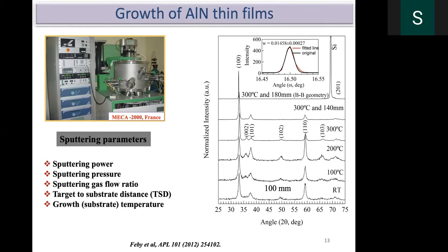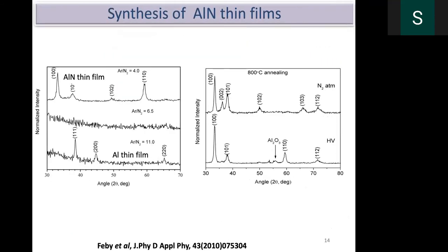crystalline films. Well, we started with aluminum nitride films, but initially we kept everything constant other than the argon to nitrogen ratio. See, argon to nitrogen ratio, if I have 11%, that means argon is higher and nitrogen is very small. In such a situation, the film is completely aluminum. Maybe a few nitrogen will be there that I did not show in the X-ray diffraction. This is the X-ray diffraction profile. When you add nitrogen further, around 6.5, it becomes completely amorphous.